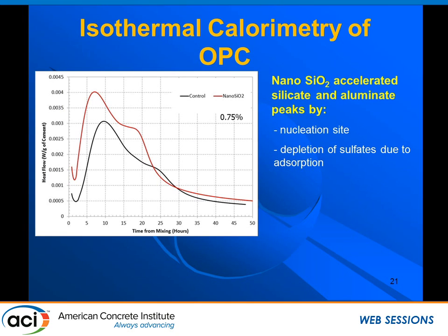When we put in nano silica—again, we have no fly ash there—only 0.75%, whereas in the previous slides it was 1% replacement. We see a significant shift to the left and an increase in the amplitude of the peaks. Why? We believe we're providing nucleation sites for CSH and depletion of sulfates due to adsorption on the surface of the nanoparticles.